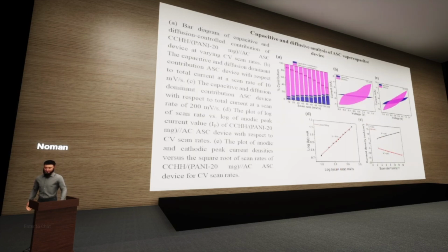Further, the capacitive diffusive analysis of the asymmetric supercapacitor device was performed to find out how much the device is behaving capacitive and how much the device is behaving diffusive. So capacitive diffusive analysis shows that the more dominant factor was the diffusion controlled mechanism involved in the asymmetric supercapacitor device, which shows that the device is more battery type, which is very good for high energy density and power density values.